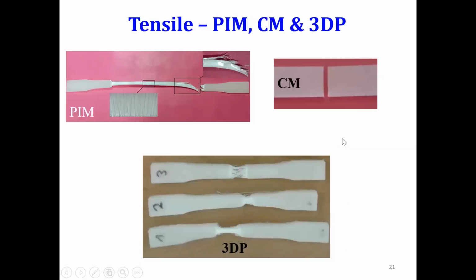One more point I want to make here is, though the material is the same, high density polyethylene, this is injection molding, this is compression molding, and this is 3D printing. The material is from the same supplier, same batch, same temperature settings. So if I'm setting 160 degrees here, I'm setting 160 degrees C in compression molding also.